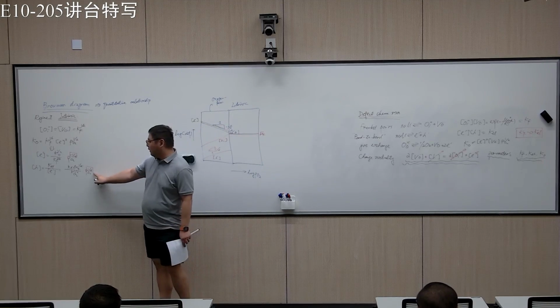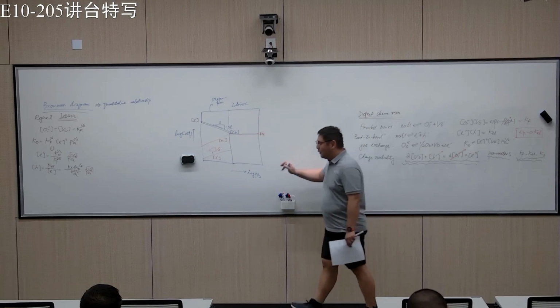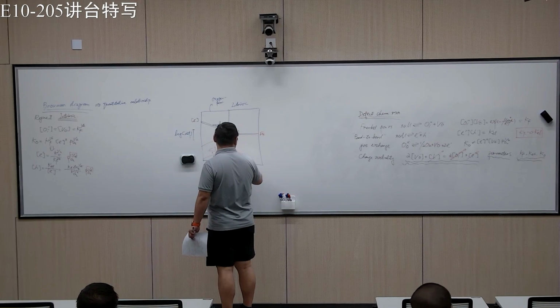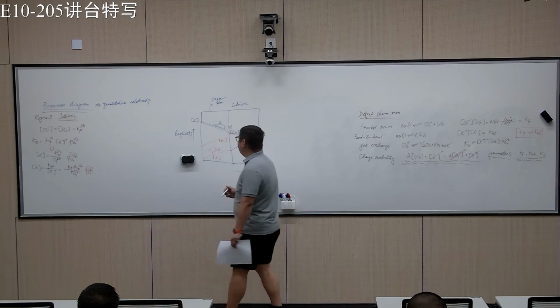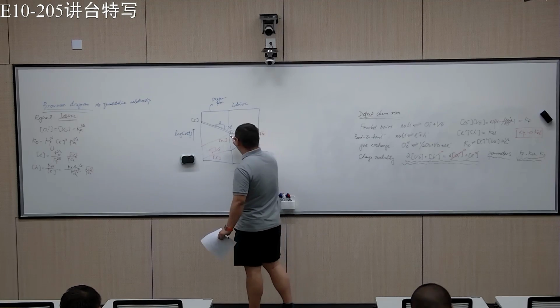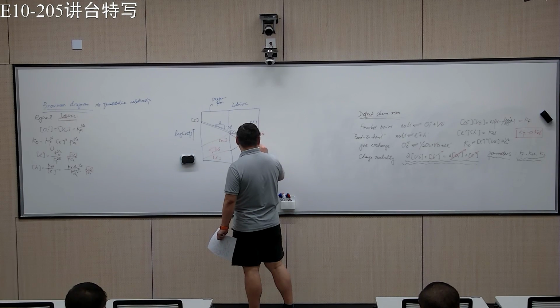Holes again have a slope of 1/4, positive 1/4, and electron is basically this line here. So this will be holes. This will be electron, with slope -1/4.